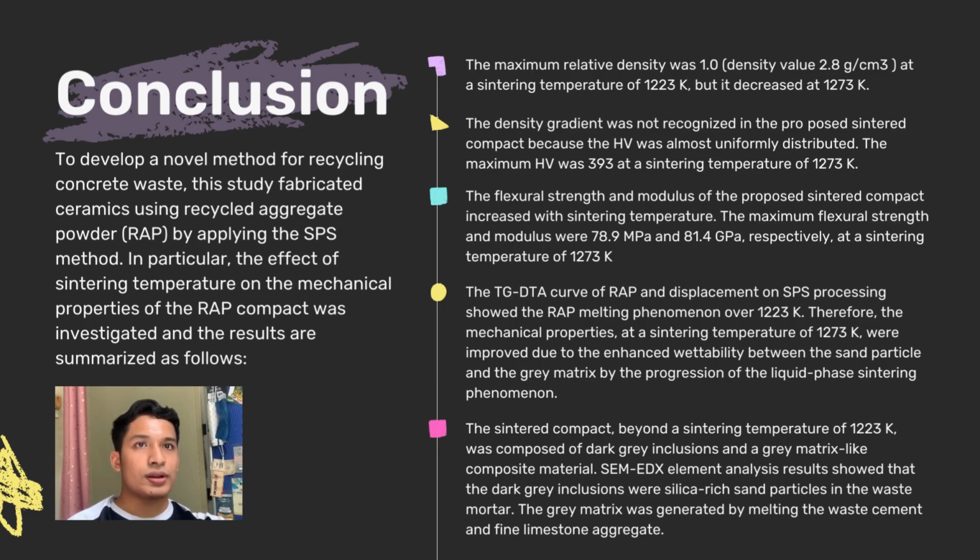The maximum flexural strength and modulus were 78.9 megapascal and 81.4 gigapascal respectively at a sintering temperature of 1273 Kelvin.